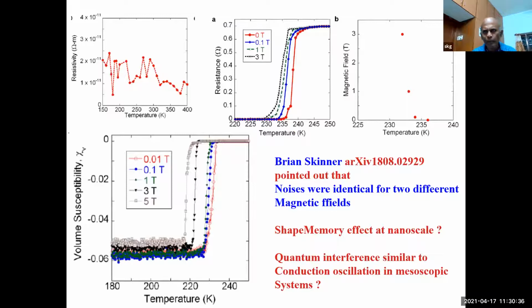So they have put out 4 papers. Again, the thing that I pasted is missing. The arXiv references: coexistence of, that's the first paper, current voltage characteristics, unconventional optical response, observation of excess resistance. So let me show some of these pictures. You see these pictures, the resistance doesn't go to 0, but it goes much lower than the metal resistance of gold or silver. And there's a lot of fluctuations.